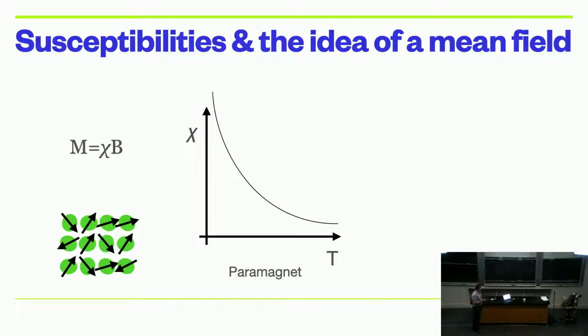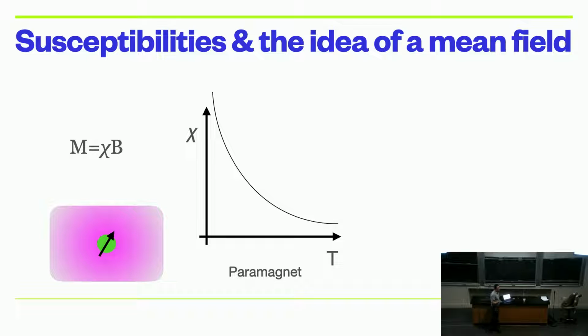But in a ferromagnet, something interesting happens, and this is what I want to tell you a bit about. In a ferromagnet, because there are now interactions with the spins in its environment, it's starting to see all the spins that are around it. The way we sometimes model this, at least in the simplest way, is what's known as a mean field. We say that a little local spin in the middle of a material feels a mean field from all the spins around it. So it's basically an approximation. And what happens when you apply such a mean field is that you get the same kind of divergence of your susceptibility as you decrease in temperature, but then as it goes through the transition, the susceptibility gets cut off. All of the spins are aligned, and you just end up having a constant susceptibility. Okay, or zero susceptibility, depending on the transition.